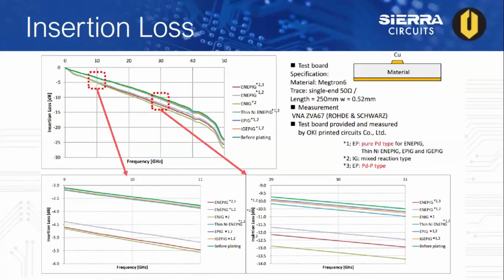Now, here is a comparison chart for insertion loss for different final finishes. When taking a closer look at the insertion loss at 10 gigahertz and 30 gigahertz, in the red boxes, the ENEPIG and ENIG show more insertion loss as compared to the advanced final finishes. The comparison plot really shows that eliminating the nickel layer will help minimize insertion loss.